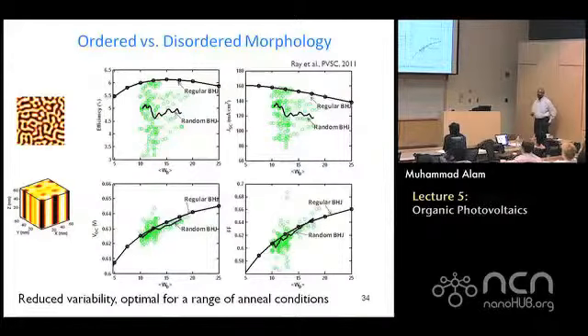The other thing is fluctuation. That is what I just mentioned, that in organic solar cells, if you have a random structure, you have huge variability in the efficiency, in the short circuit current, in the fill factor, in the VOC. Why? Because every structure is slightly different. And so therefore, you'll have huge variability. So for example, this is WD as a function of the anneal time. The longer you anneal, the coarser it gets, right? All those regions are getting thicker. And so you can see that this whole trajectory is evolving. And each point is for one of the cells. Now, if you are interested in publishing in Nature and Science, or the important journals, you can try a lot of them and pick this one and publish.